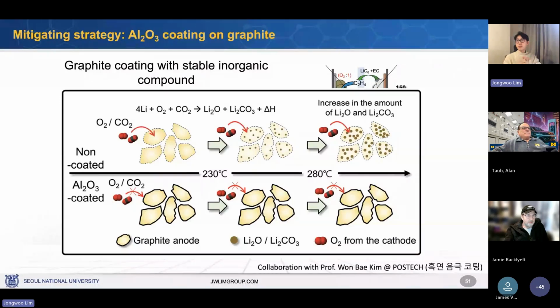Not during the thermal runaway, during the cycling, right? I think so. We haven't checked the low temperature yet, we only checked the room temperature cycling. And the aluminum oxide, surprisingly, if you control the thickness very carefully, it actually helps capacity and also kinetics. However, it's a hypothesis. It makes very friendly SEIs, and we know that the kinetics and cycling depend on the SEI formation.